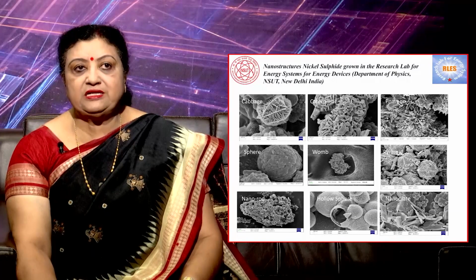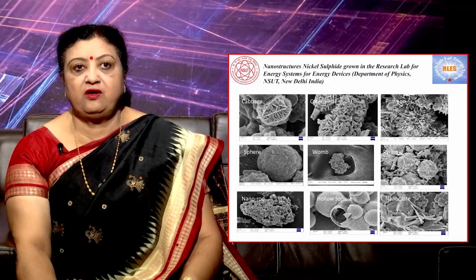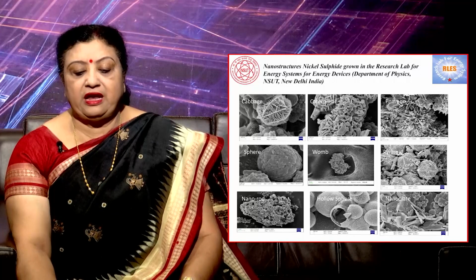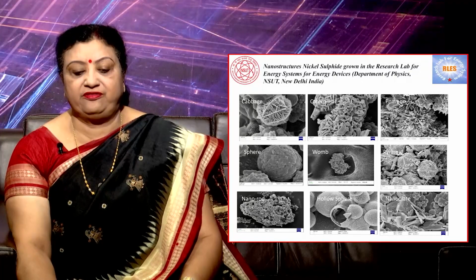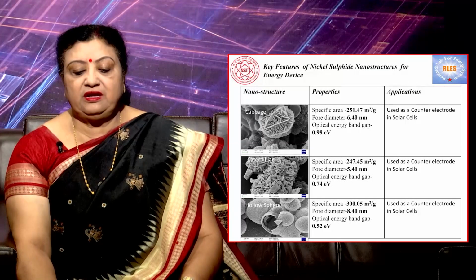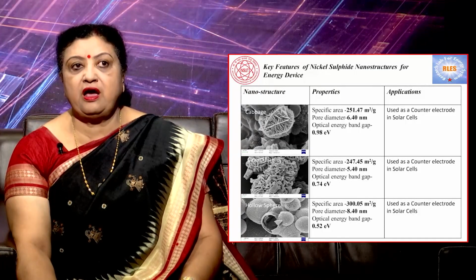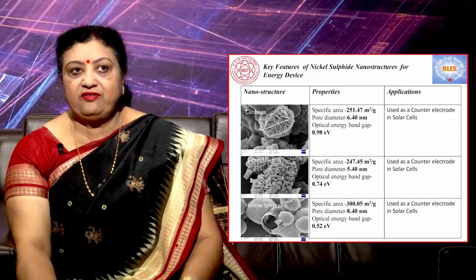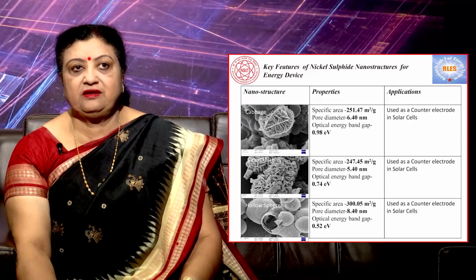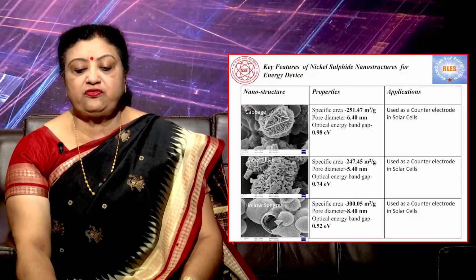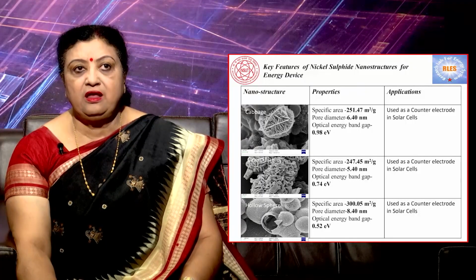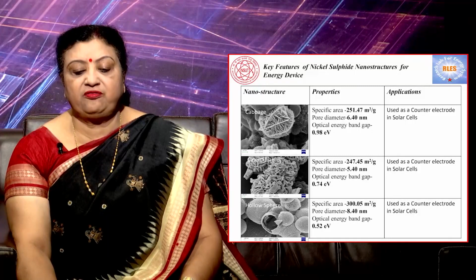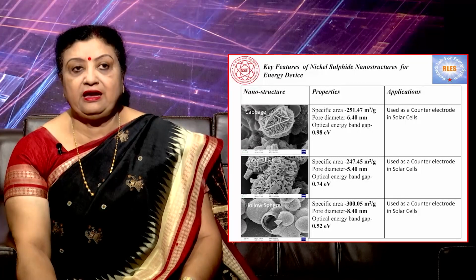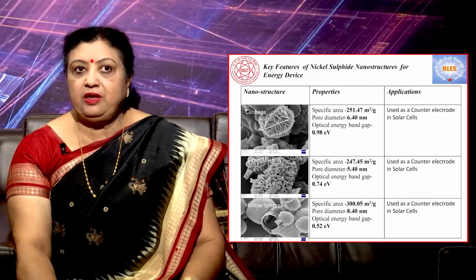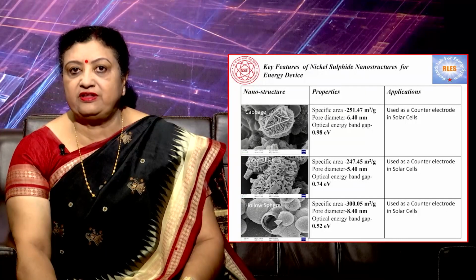They are the cabbage, caterpillar, pompon, sphere, womb, pyramid, nanorod, hollow sphere, nanoplates. So, key features of the nickel sulphide nanostructures which we are using for the energy device. The nanostructure cabbage has a specific area of 251.47 meter square per gram. Pore dimension is of the order of 6.40 nanometer. Optical energy band gap is 0.98 electron volt, and it can be used as a counter electrode in solar cells.